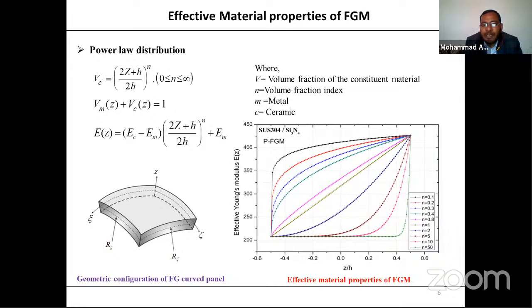So here the effective material properties vary in the thickness direction only, and for that we consider a power law distribution. Here the volume fraction of the ceramic depends on the thickness coordinate z by h and index n. By selecting the value of n, we get different volume fractions of the ceramic. Using the rule of mixture, the volume fraction of the ceramic plus the volume fraction of the metal will be 1, and accordingly we get effective material properties of the structure like Young's modulus, density, Poisson's ratio and other mechanical properties. So Ez is equal to Ec minus Em into the volume fraction of the ceramic, plus Em.